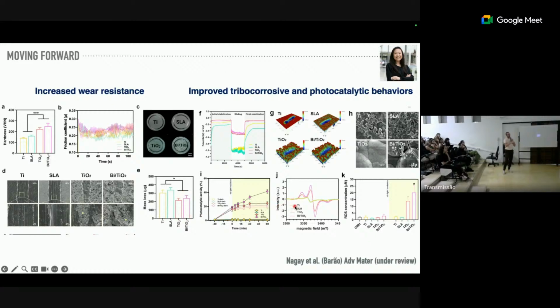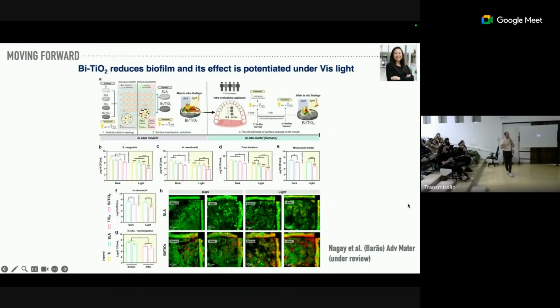We also have the photocatalytic effect under visible light. As you can see in different techniques, we observe a greater photocatalytic action for the titanium bismuth. When you have the bismuth, the effect was higher. I'm sorry because the image is not so high, but we use different techniques. We use different biofilm models to verify the antimicrobial effect. In that first study, we use a model with only 2 bacteria that does not resemble what happens in peri-implantitis. But here, we also run, again, using the same bacteria in the beginning, but we go further.